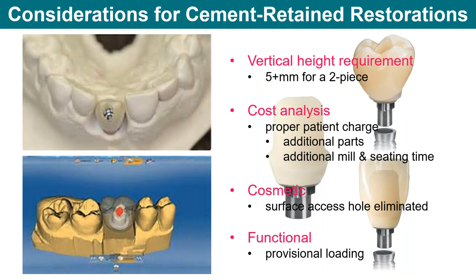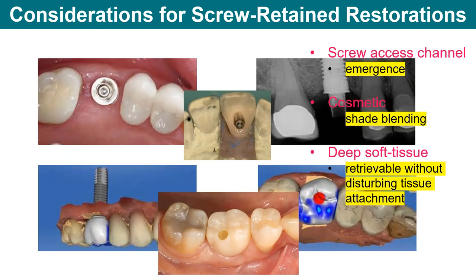If you want to do a cement retain, no problem with enamic. You can actually make a primary abutment made out of enamic, and then on top of that, you can do any other glass material on it because the implant abutment material made out of enamic will still absorb a lot of those stresses. But there's requirements, right? You have to have enough height for cement. You also then have to have the implant placed correctly. It hides the screw access channel, if it's not treatment planned correctly. Sometimes you have to go to a screw retain.